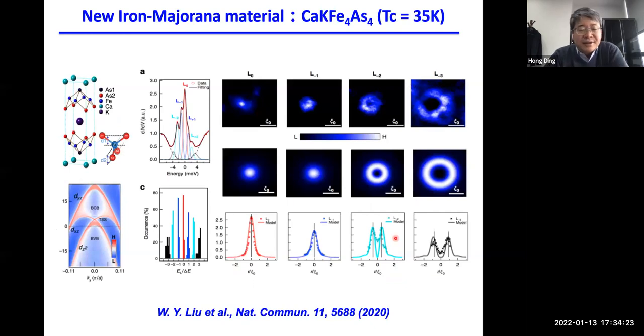After finding the zero mode in iron selenium tellurium, we had to think about finding more iron-based superconductors hosting Majorana zero modes, because iron selenium tellurium is doped, a mixed half-half. So they have quite a lot of disorder in the bulk and on the surface. So it's not very good if one wants to do braiding, or even to see a uniform zero mode. So we have to look for a more uniform, non-doped, essentially homogeneous material. One of these is calcium potassium iron four arsenic four.